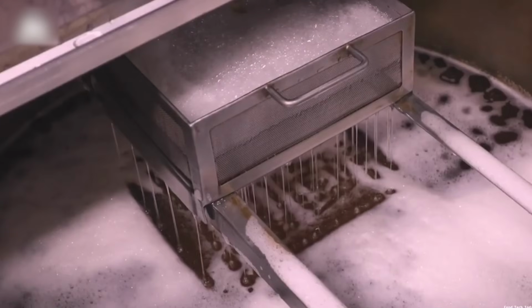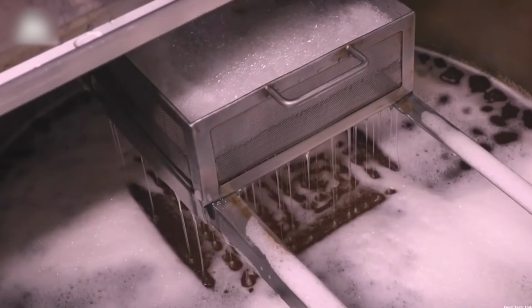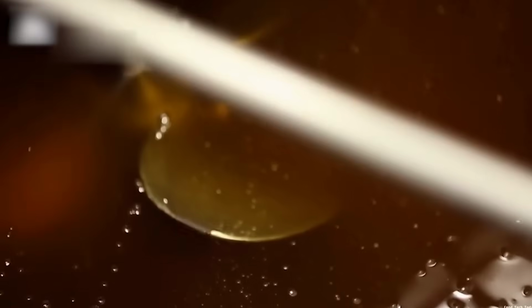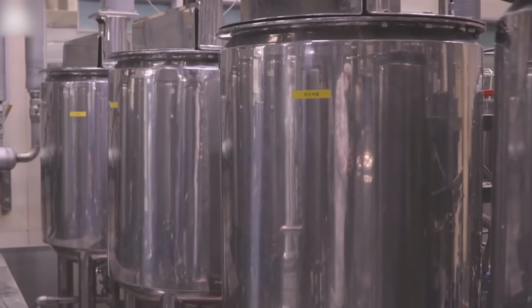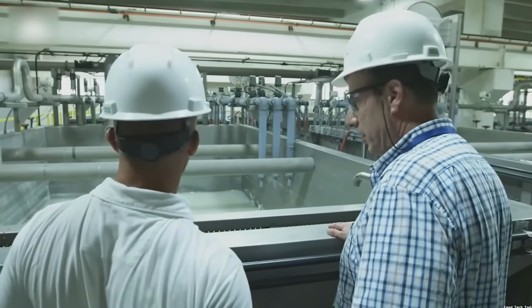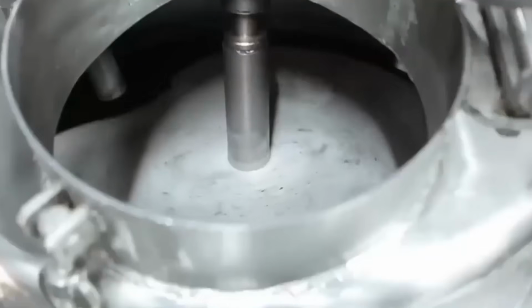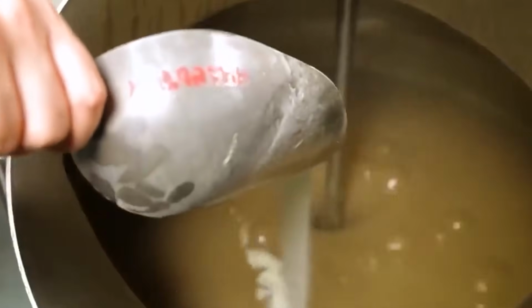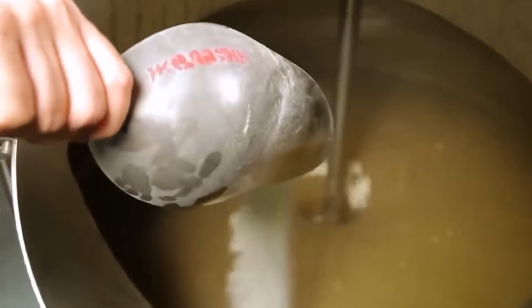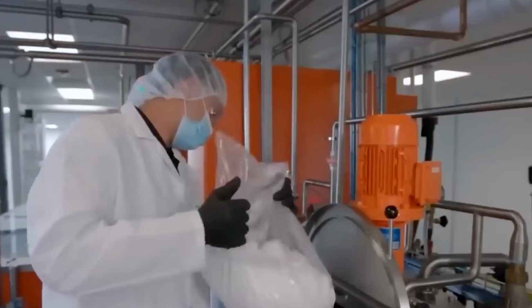After cooking, the syrup is cooled to protect sensitive additions and to set the right viscosity for casting. Cooling is done with heat exchangers that drop temperature along a controlled curve. Acid addition is often delayed until after this cooling because high heat can accelerate sucrose inversion and change texture. When the syrup reaches the blending temperature, acids are injected as solutions for rapid dispersion. The acid level sets the tartness and also influences shelf stability by affecting water activity behavior.